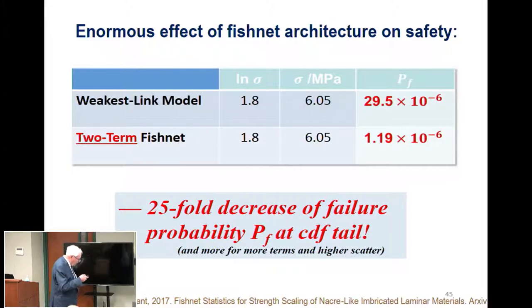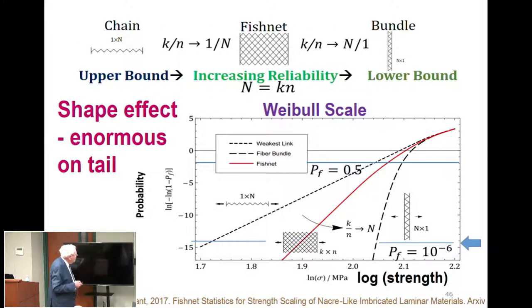Now in terms of probability, the conclusion is that with two-term fishnet, you decrease the probability of failure 25 times. So enormous contribution to the safety of the material. With three terms, somewhat more. Now an interesting point is the fishnet is this. You can change the shape, square in this case. You can increase the number of rows, decrease the number of columns, you get a bundle.